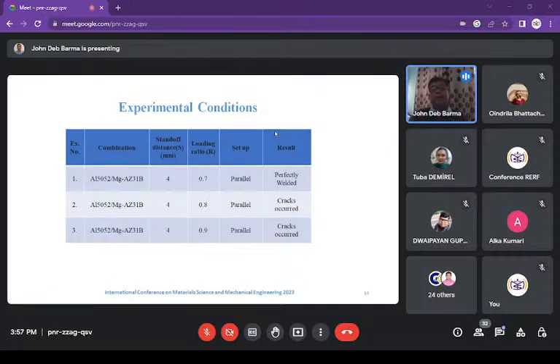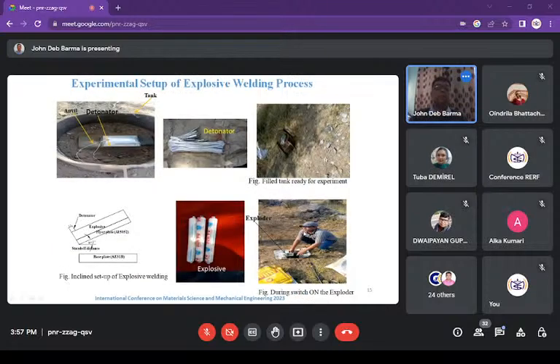And these are the different experimental conditions. Stand-off distance in this particular topic is kept as 4 mm. There are different loading ratios, and a parallel configuration has been kept. And the result is, whenever we have gone for 0.7, it was perfectly welded. When we have gone for 0.8, cracks occurred. Whenever we have gone for 0.9, again we have seen cracks. So this is the experimental setup of the explosive welding process that we have followed.